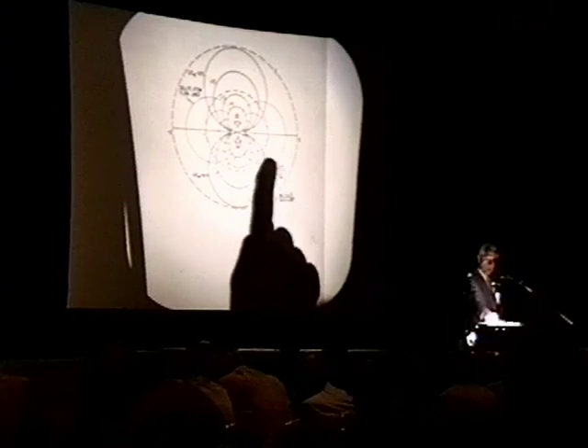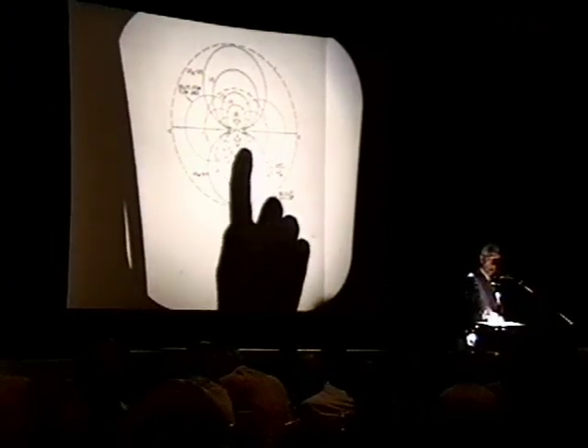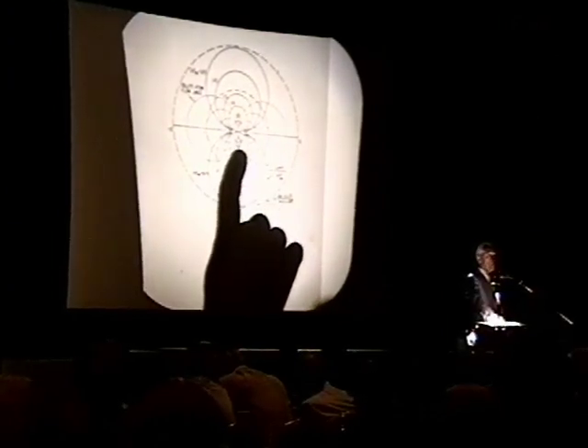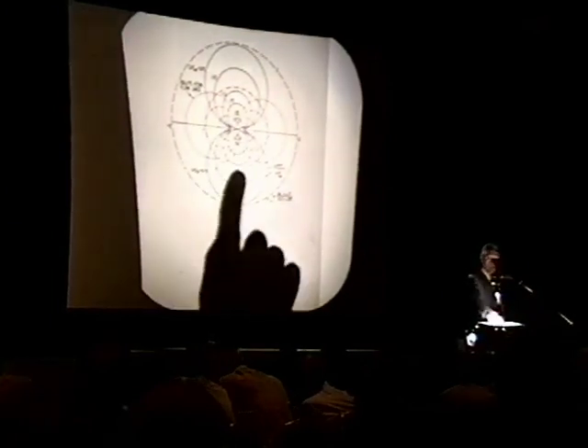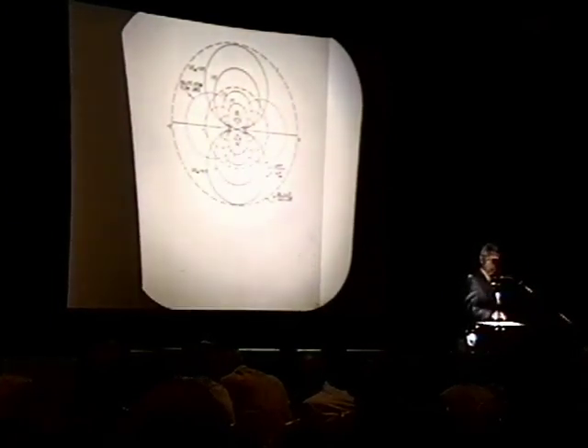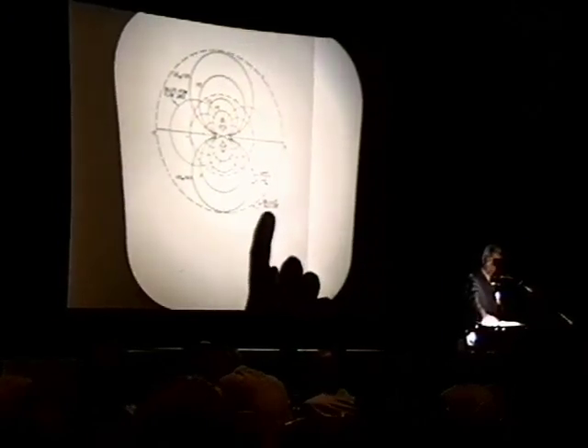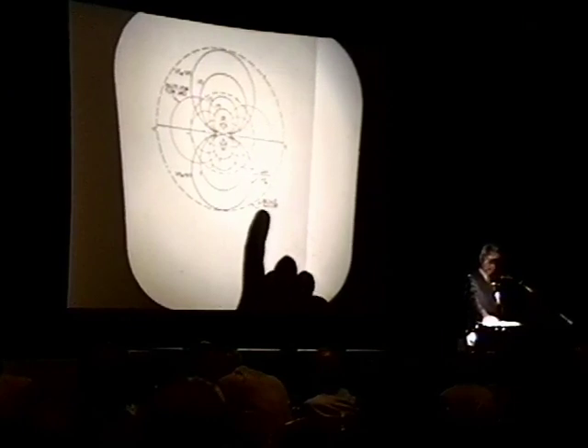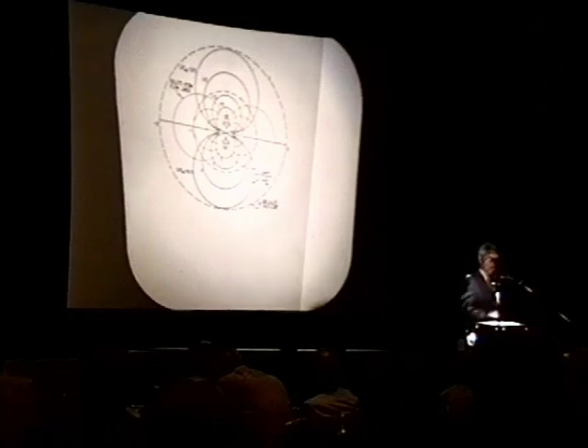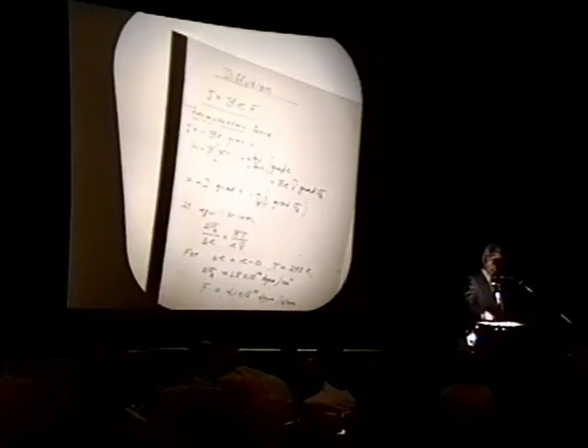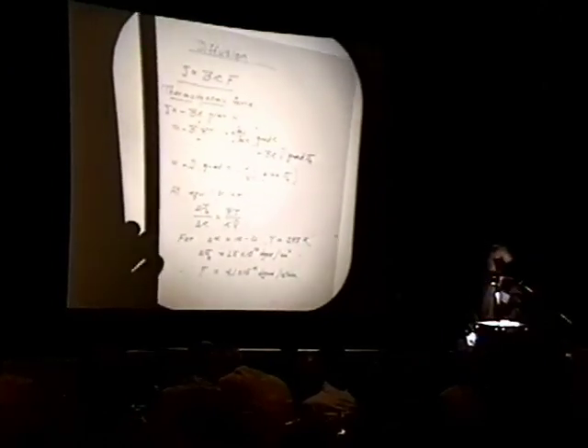These are isoconcentration lines. Here we have a ratio of 50 between the original stress-free concentration and the existing concentration in the stress field. And you see how this goes. The radii are given in terms of elastic parameters. G is the shear modulus, b is the Burgers vector of the dislocation, nu is the Poisson ratio, and V-bar is the partial volume of hydrogen. I don't want to take much time with that. Let's go on to some kinetic considerations for hydrogen in metals.